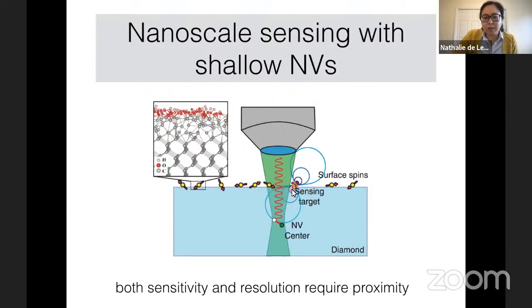And while we're very good, as mankind, at making extremely high purity bulk diamond, we're generally quite bad at making good surfaces. It turns out we're actually really bad at making most surfaces, but diamond surfaces are even harder than other surfaces. So what happens is you see this background spin bath, and that obscures the signal that you would like to see coming from your sensing target.